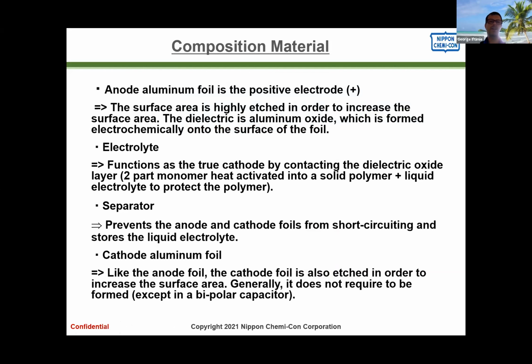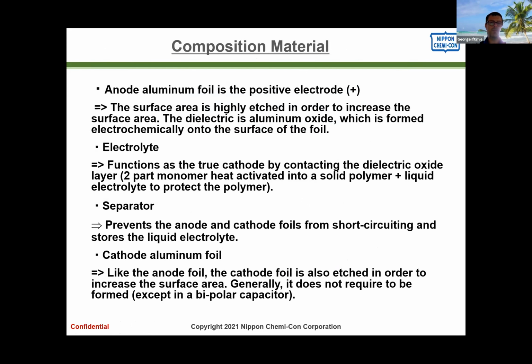And of course, there are a lot of variables on hybrids. Playing with the type of polymer and the type of liquid electrolyte will make a big difference in how the part performs. Also, playing with the ratio between the polymer and electrolyte will change how the part behaves. If you have more polymer and less liquid, you're going to have a quote unquote better part electrically: a lower ESR, longer life, higher ripple current. But then the downside is that it's going to be weaker to humidity because you have less electrolyte, which will eventually evaporate.